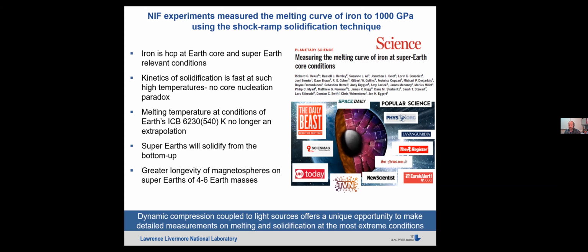Given how we can take the iron from the pressure-entropy state to the pressure-temperature plane using experimentally constrained derivatives, we find the melting temperature at Earth's inner core boundary of 6230 plus or minus 540 degrees, which is no longer an extrapolated measurement, but is in an interpolation regime. Given that we observe pressure-driven solidification over the range of states of our experiment pressures, we find that super Earths will solidify from the bottom up, which enhances their ability. Top-down solidification doesn't necessarily stop dynamos, but it's found that bottom-up solidification powers them the best. And the greatest longevity of a power source to drive a dynamo, and thus of magnetospheres on super Earths, occurs in the 4 to 6 Earth mass regime.